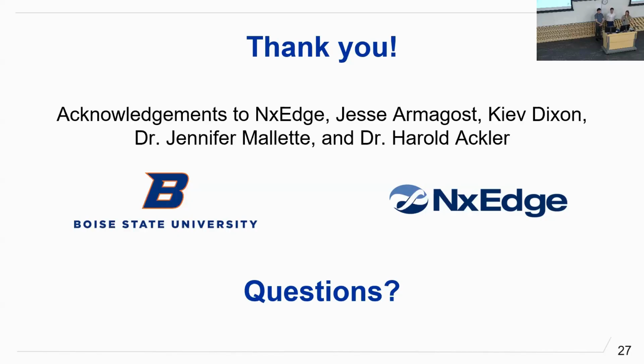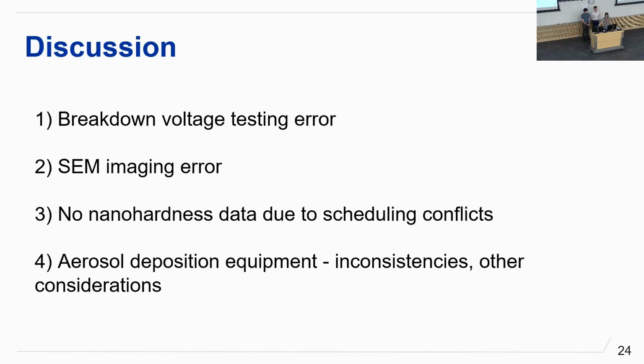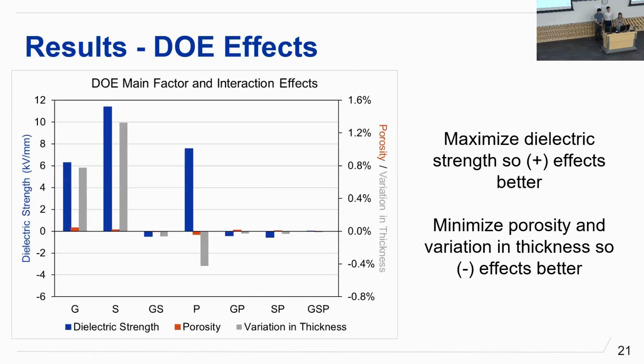Another question. Your DOE should give you an idea of what the most influential process parameter is, and maybe I missed it, but what's the most influential process parameter? For each response or the overall recipe? Overall, I believe it was gas flow rate. Or stage speed, probably, because it increases dielectric strength the most, and it increases variation in thickness the most, which is not what we want, but it is influential for determining the variation of thickness. So stage speed. Any other questions?